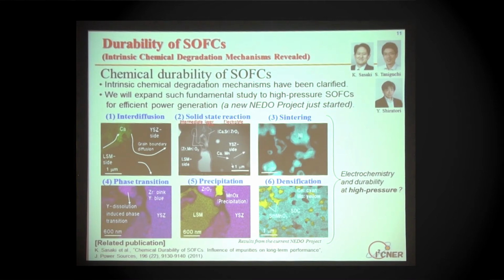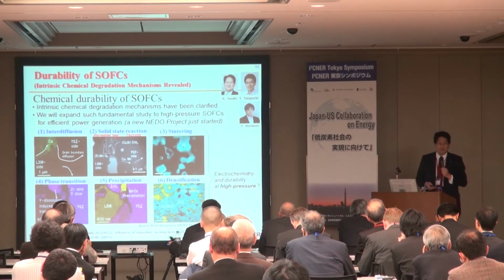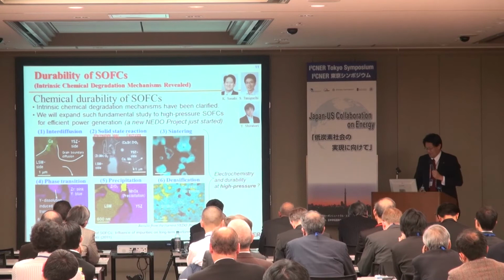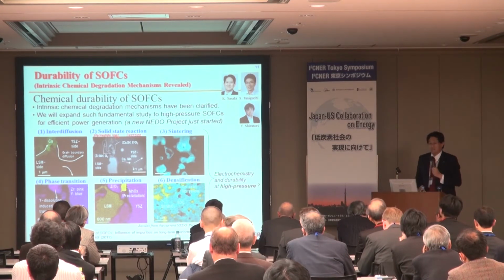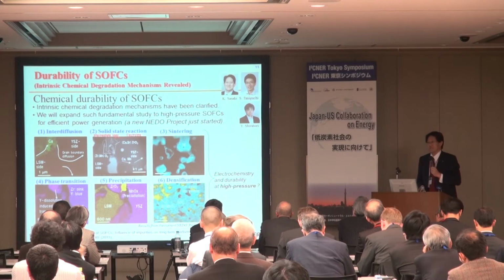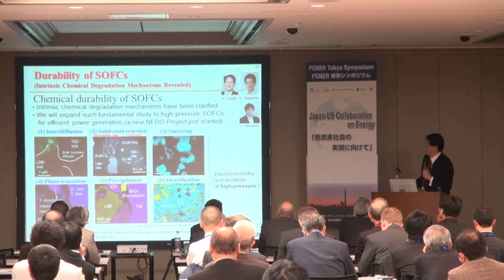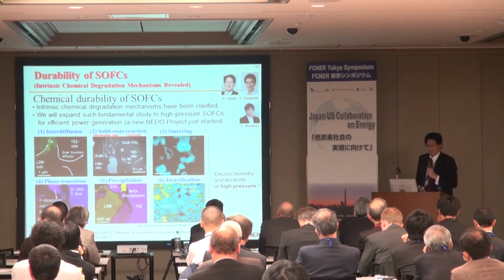We also found that the sintering of the catalyst material, in this case nickel, is also very important. And of course, we should manage to keep the microstructure during the high temperature operation for a long time period. We have also found that dopant in the electrolyte can dissolve into the grain boundaries. And that can cause a problem, for example, during cycling, and that must be prevented. Of course, we have clarified such degradation mechanisms determining the lifetime. But the challenging topic is, of course, the degradation issue at high pressure.